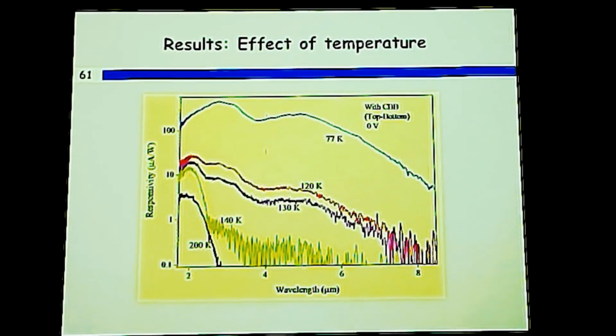Again, we are interested in higher temperature. Looking at the temperature effect from 77 K to 120 K, we see a significant reduction in the strength of the photoresponse, and that is up to 130 K, but after that, that photoresponse is mostly limited in the range of 2.5 micron or so, which corresponds to the high energy blocking barrier. Now the rest of the device appears to be not active at high operating temperature.